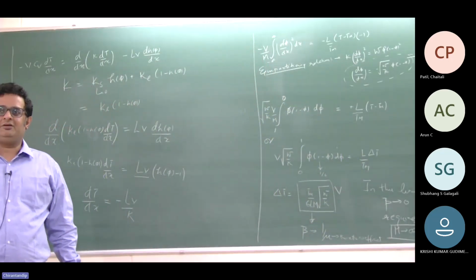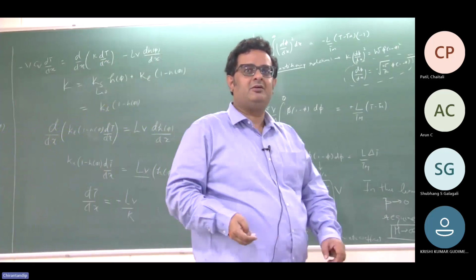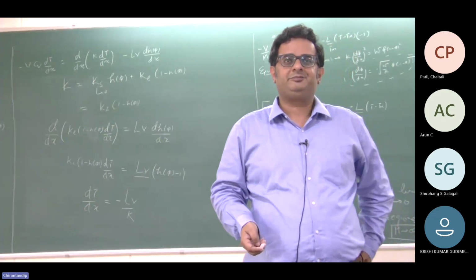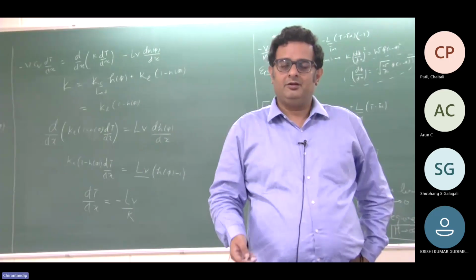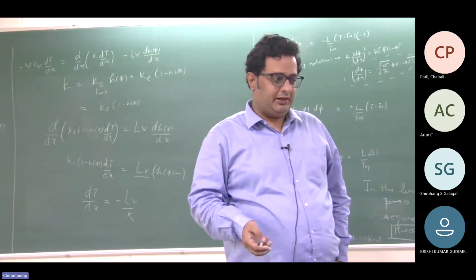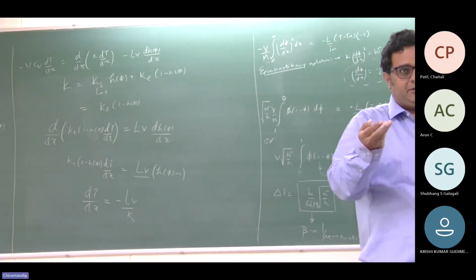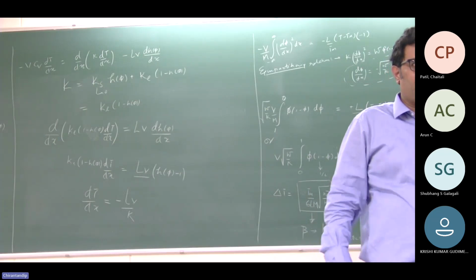If we get the interface width experimentally, so we input that interface width in the simulation. Yes. So whatever is happening is actually happening. The point is this: if you were to actually put in a physical interface width, about 10 to the power minus 10 meters, interface widths in experiments are of that order, as small as angstroms.